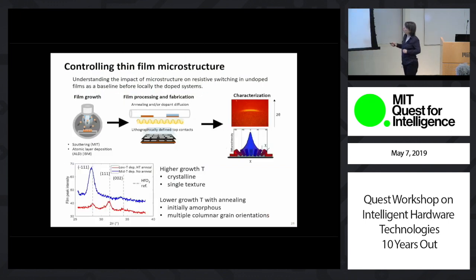So we perform these samples by physical vapor deposition, by sputtering at MIT, and we also get samples from our IBM colleagues where they prepare the hafnium oxide layers by atomic layer deposition. And all these samples that we prepare differently, we can also subject them to different annealing, gas environment, and dopant diffusion conditions. And then we characterize their microstructure by X-ray scattering and their electrical properties by electrical characterization.